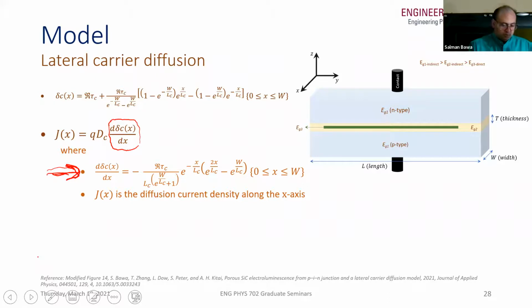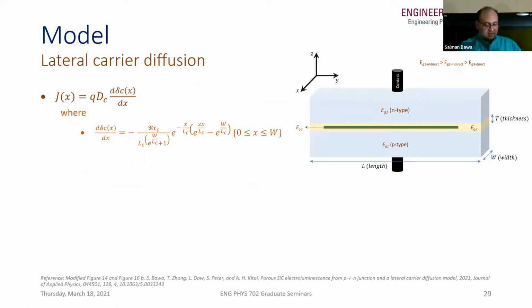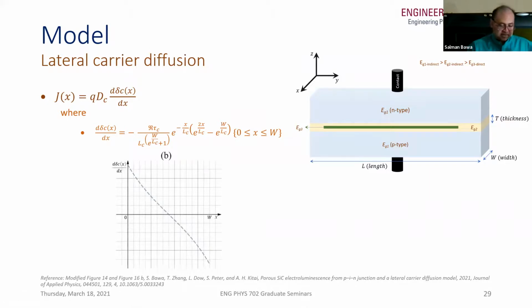And we also see that the current density, the diffusion current density, is proportional to the differentiation of the change in carrier concentration. So when we try to plot that, here's what we get. And this is exactly what we had hoped for, where if the carriers are being diffused to the edges, the diffusion current density at the edges would be maximum and would be 0 at the center of the device. Now, at x equals w, we are getting a negative value. What it basically means is that the diffusion current density is maximum at x equals w, but it's just in the opposite direction of x equals 0.